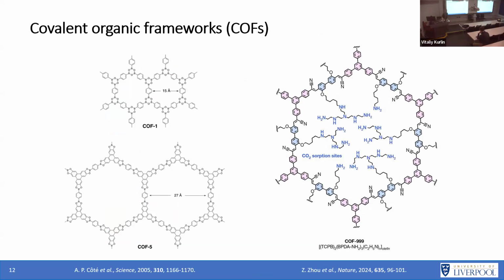You've also got other related structures to metal organic frameworks, and these are called COFs, or covalent organic frameworks. As the name suggests, they also don't contain metals, they're purely covalent structures. So these were discovered maybe 20 years or so ago by Omar Yaghi, and this is a couple of the first ones. So you've got COF-1 and COF-5, and these are based on boronate type linkages. And essentially, these are also highly porous structures. They're very regular structures. They're very stable structures. But one thing I will say is they're not particularly crystalline. So when we talk about metal organic frameworks, typically they're nice and crystalline when they form. COFs are not really. If you've worked with them, you will certainly know that.